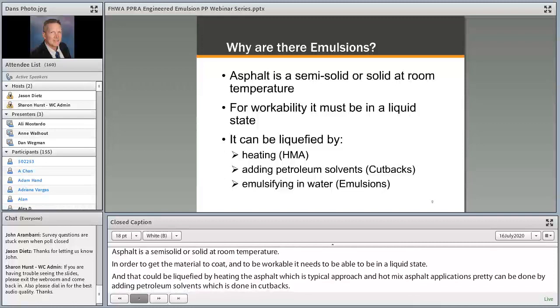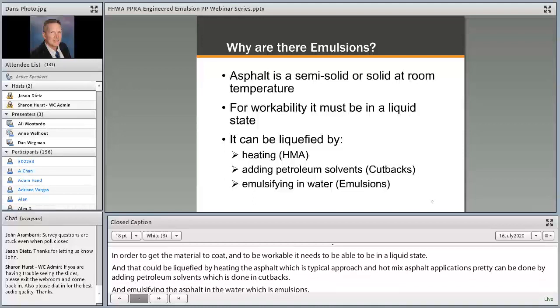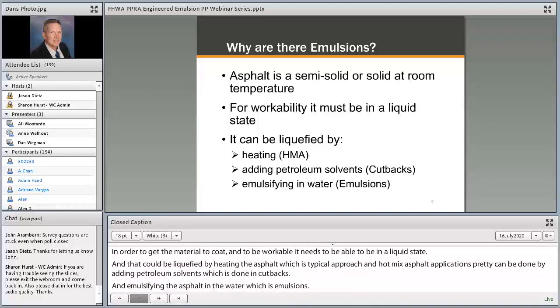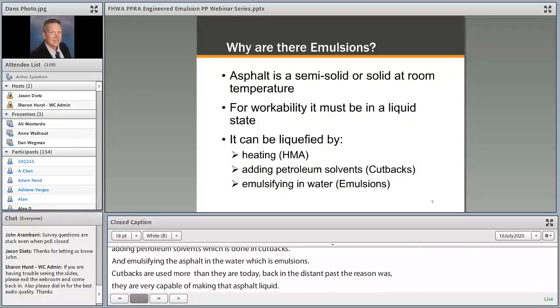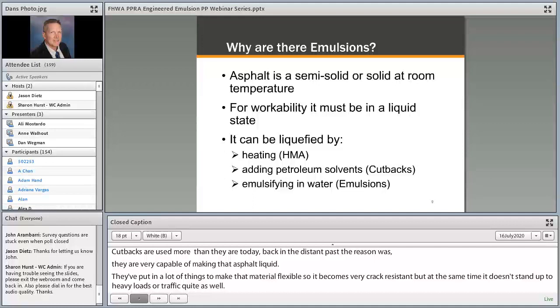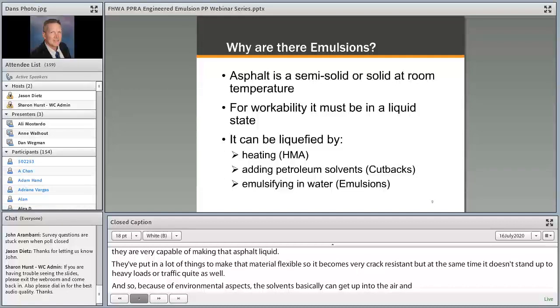Now, cutbacks were used significantly more than they are today back in the distant past. And the reason was they are very capable of making that asphalt liquid. In fact, they put in a lot of light ends that make that material very flexible, which means that it becomes very crack resistant, but at the same time it doesn't stand up to heavy loads or traffic quite as well. And so because of environmental aspects, the solvents basically can get up into the air, and because of the very flexible nature of it in terms of the increased traffic loading and heavier loads, cutbacks have been used substantially less now, and a lot of that volume has gone over to emulsions.